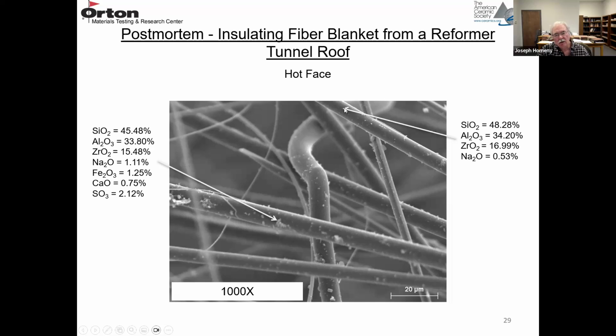So here's the chemistry of a clean region. It's an AZS fiber, about 48% silica, 34% Al2O3, and about 17% zirconia. So it's a high temperature AZS fiber. And then the contamination that's starting to appear, SO3. So there's a sulfur compound, and it looks like it's also picking up some lime and maybe a little bit of iron oxide.